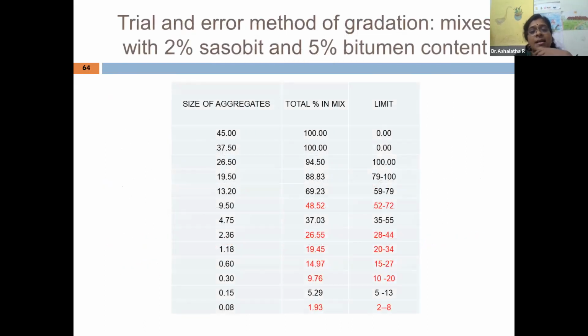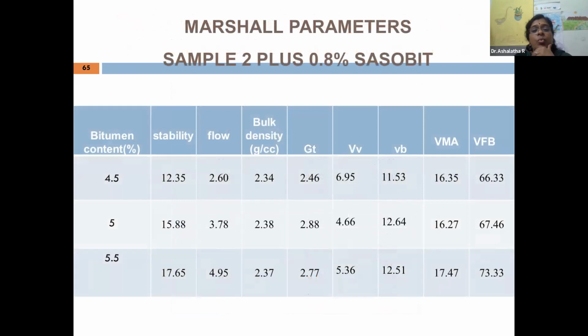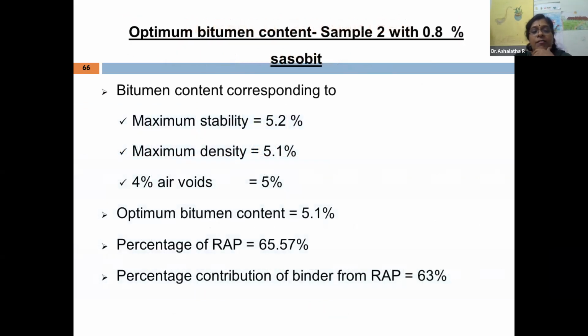So this is what I said, the trial and error process with 2%. Since it was not satisfying the required gradation, we went with 0.8% Sasobit, and these are the Marshall values. And then we found that optimum bitumen content comes to around 5.1%, percentage of the RAP as 65.57%, and the percentage contribution of the binder from the RAP is 63%.